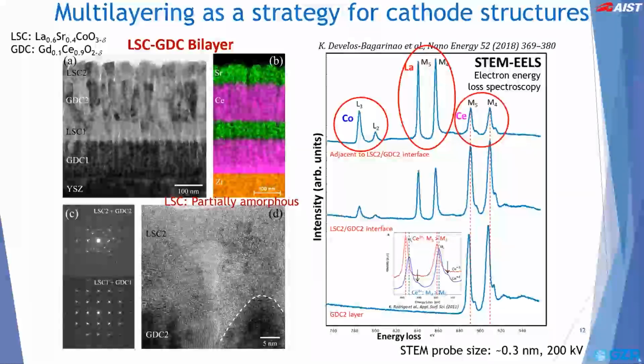In particular, we were interested in looking at the changes of the cerium peaks. The ratio of the intensities of the M5 and M4 peaks provide information on the valence state of cerium, meaning we can get some quantitative information of how the valence state of cerium changes from 4+ to 3+ across the LSC-GDC interfaces.